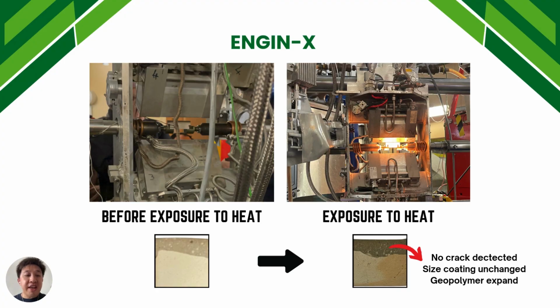Now, we also carried out testing using Engin-X. This is before exposure, using Engin-X at ISIS, Oxford, UK, and on the right hand side we can see the sample after exposure to heat at 800 degrees Celsius. As we can see, left hand side before exposure to heat and right hand side after exposure to heat, there is no crack detected. The size of the coating is also unchanged, and the geopolymer expands, but the size still remains the same.